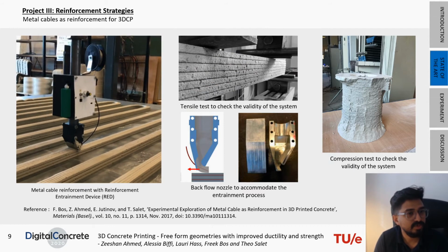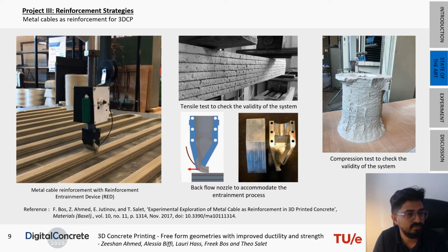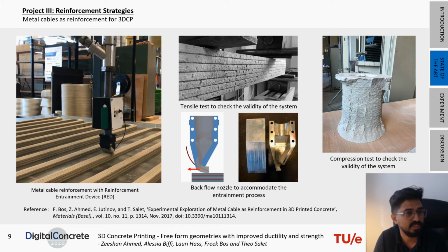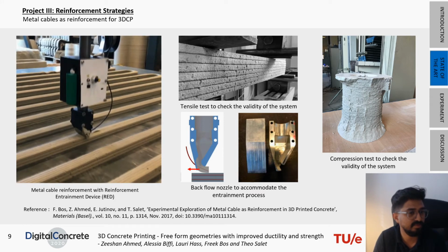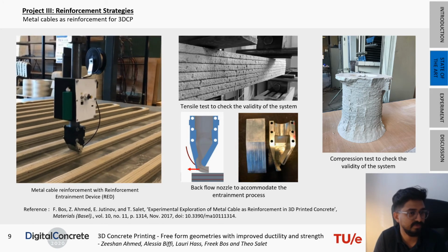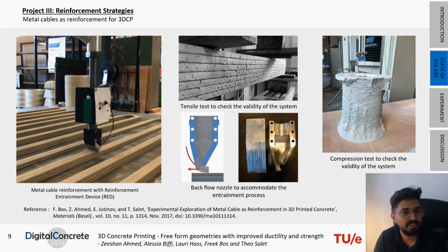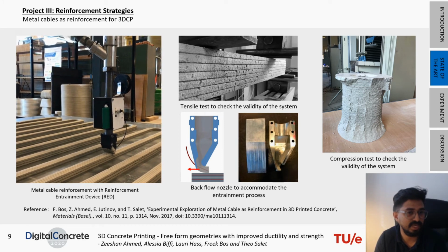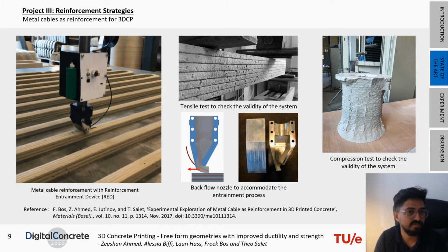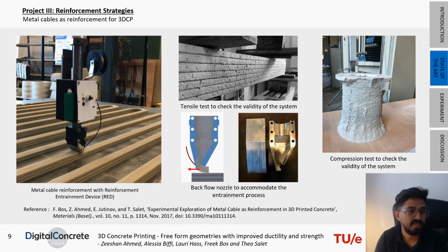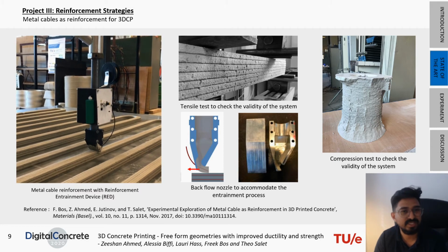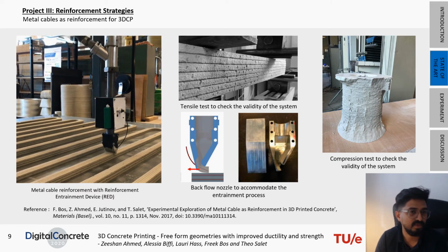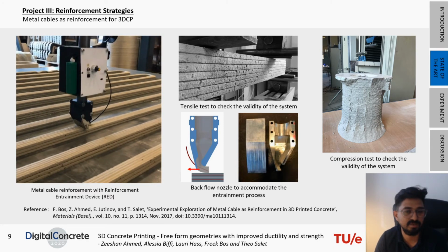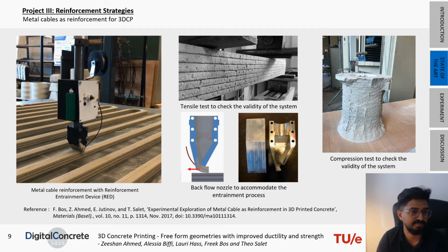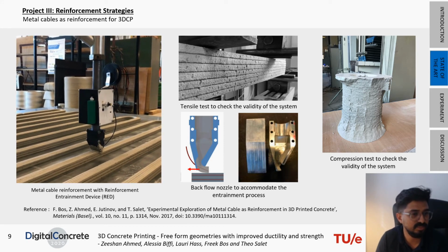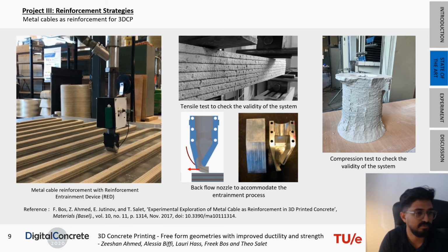Moving on, the third project is on introducing reinforcement into the printed concrete, for which a special device called the reinforcement entrainment device, in short RED, was developed. Special nozzles with a backflow extrusion needed to be prepared, and this backflow extrusion accommodates the entrainment of these cables. This entire system was tested with various tests like the tensile test and compression test to check the validity of the system. To know more about the test results, please refer to the reference given below.